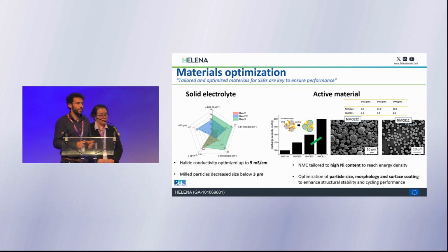On the experimental side, there's been a lot of materials optimization. If we take the solid electrolyte as a core material here, our industrial partner has been able to manufacture several generations of this halide electrolyte at a large scale. And with that, they managed to obtain a high conductivity material with 5 millisiemens per centimeter, which will ensure, hopefully, the performance at higher rates. And also, as an important property of the material, they managed to decrease and to homogenize the particle size to ensure a good contact between all the materials within the battery.